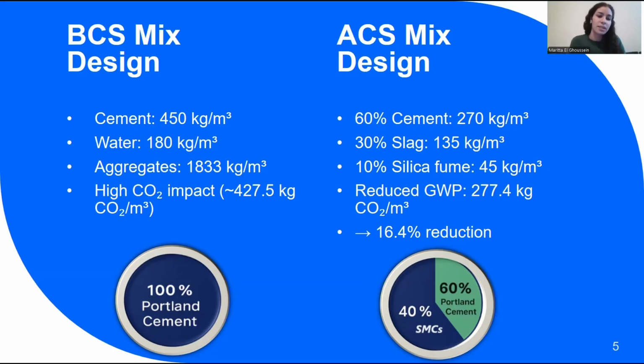Now to talk about the BCS and ACS mix design, let's start with the BCS. This mix followed a traditional concrete design made entirely with 100% ordinary Portland cement as the binder. It also included natural aggregates and water. We have 450 kg per cubic meter cement, 180 water, fine and coarse aggregates 1,833 kg per cubic meter, and a high CO2 impact calculated to be 427.5 kilograms CO2 per cubic meter. This is the kind of mix commonly used in industry, but it's also the one with the highest environmental footprint.